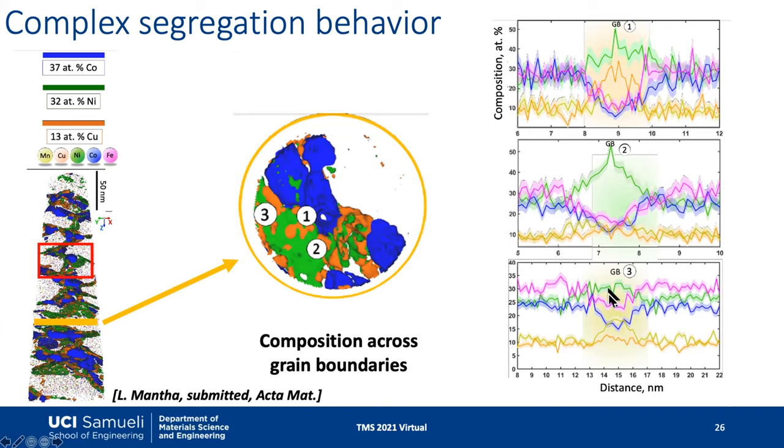manganese and nickel. This is showing that interfacial phenomena are highly dependent on the local chemistry at each type of interface, depending what kind of grain boundary character it has, and more specifically, at each atomic site in the boundary.